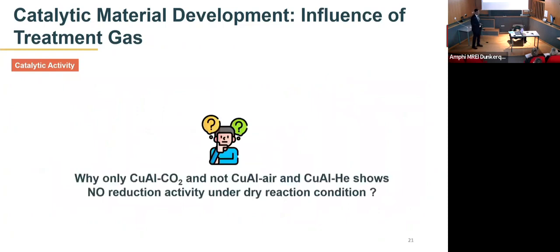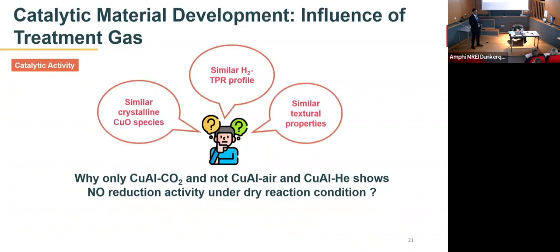However, for us, it is important to see why the carbon dioxide treated sample showed us NO reduction activity under dry reaction condition, while not the air or the helium treated sample show us the same activity. Even if we had the similar diffractograms of the crystalline species of copper oxides, we had the similar TPR profile for all these three samples, and we had the similar textural properties for all these three samples.